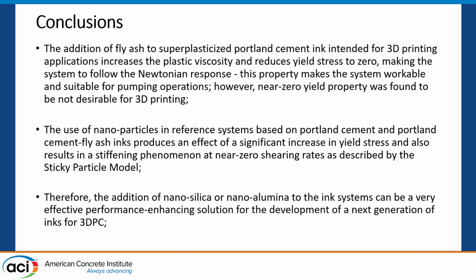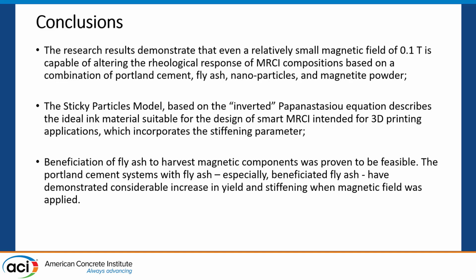Again, what we see is that if you just simply use fly ash systems, sometimes it's difficult to achieve the desired performance. Obviously, we can improve it with nanoparticles, and nanoparticles can provide the desired response with sticky particles, which we described by the sticky particles model. This can be a good solution. But if we want to design the magnetorheological response, and our field was 0.1 Tesla for this experiment, this can really change the rheological response, but we need to be very careful in balancing the type of nanoparticles and the type of magnetic particles we use in the system, if we want to be effective.